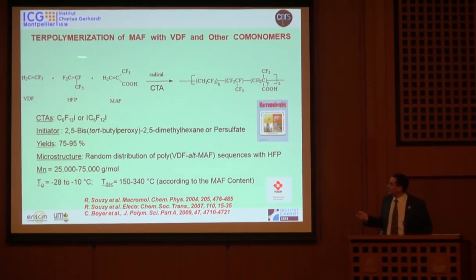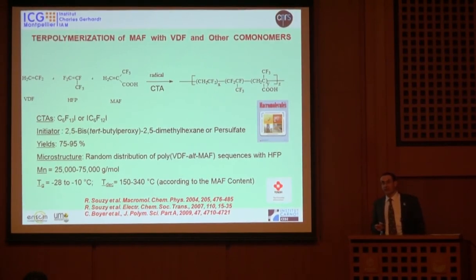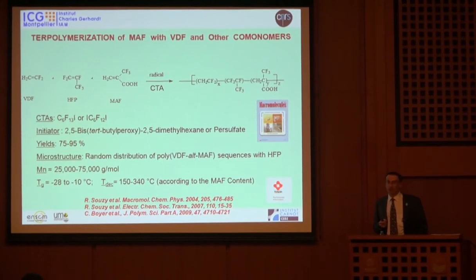So the approach we had was to try to find out again some copolymerization with VDF, vinylidene fluoride, hexafluoropropylene, and this monomer. I say this is the cousin of acrylic acid. But acrylic acid polymerizes very easily. But if you put a CF3 in alpha position, it does not homopolymerize. This is a unique sample given by Tosoh Company. Tosoh Company is in Tokuyama, and they supplied us this sample. So I'm very thankful for this company which enabled us to get this sample.